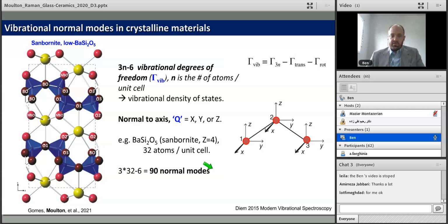On the left-hand side of your screen is the unit cell of the mineral sanbornite. Sanbornite has a relatively simple composition, barium disilicate, BaSi2O5. And it's a Q3 phase with sheets of tetrahedra that extend in two dimensions, and they're separated by these large barium atoms. And so you probably know that Raman fundamentally probes the vibrational modes of these crystalline materials. So any crystalline phase has 3N minus 6 vibrational degrees of freedom.